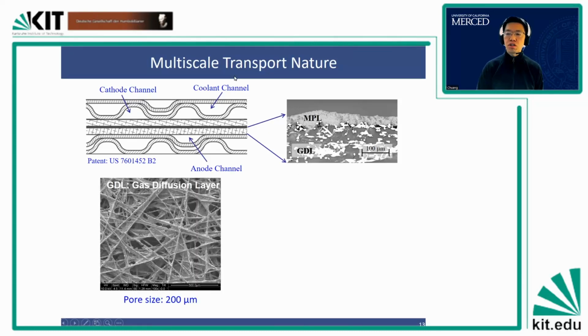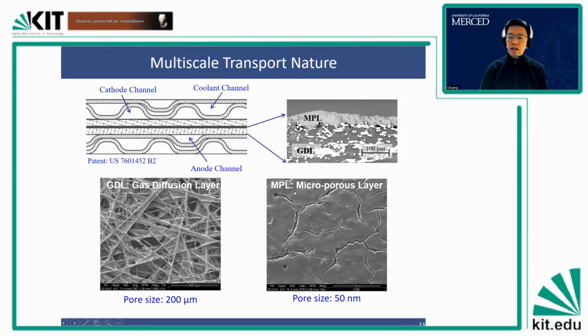And I use this to show you the multi-scale transport nature, because the gas diffusion layer is actually made of carbon fibers, where the carbon fiber size is about 7 to 10 micron each. When you stack them up together, the pore size is about 200 micron. Then the microporous layer, which is a layer on top of this gas diffusion layer, consists of carbon particles mixed with hydrophobic agents like PTFE. There are some large cracks on top of it, but the pore structure within these carbon particles is roughly about 50 nanometer.